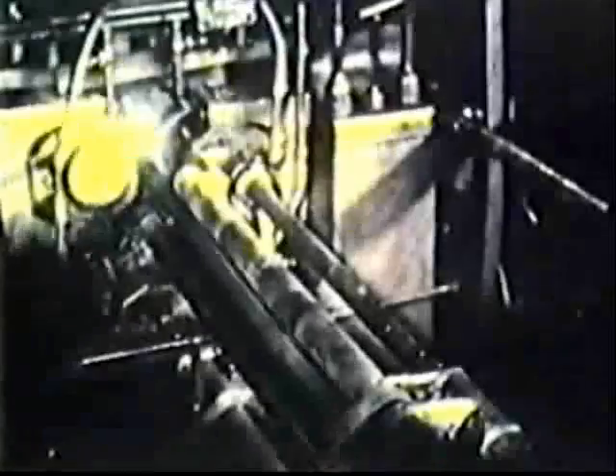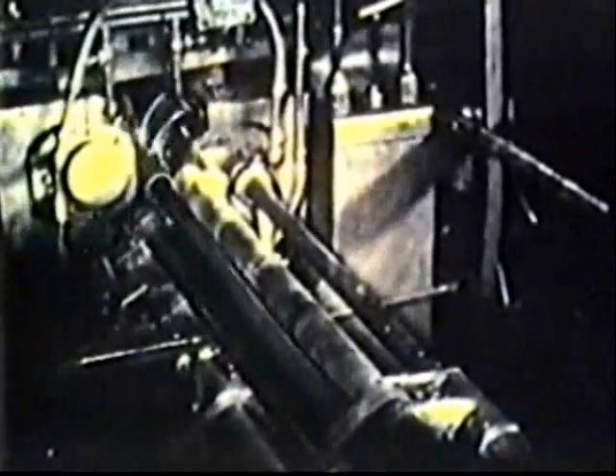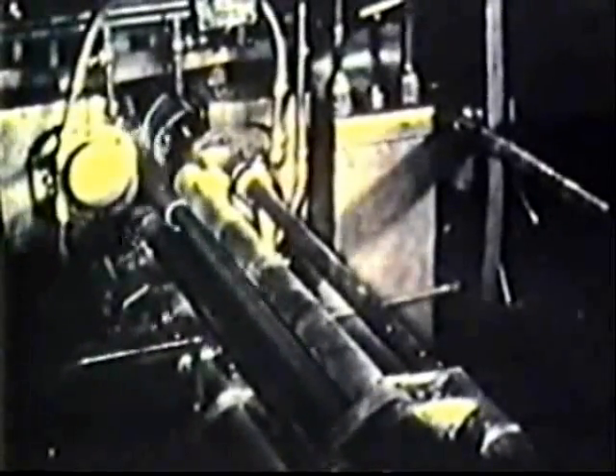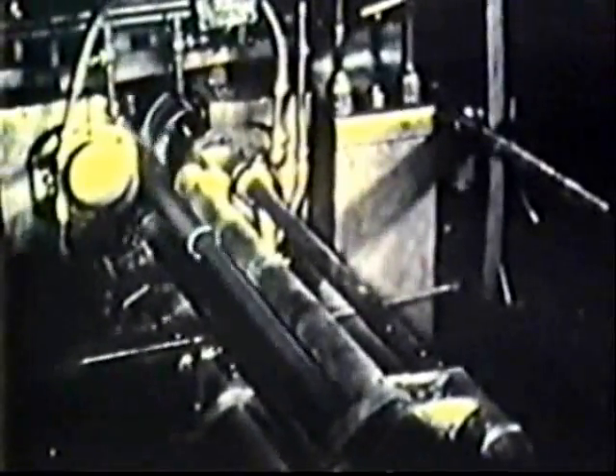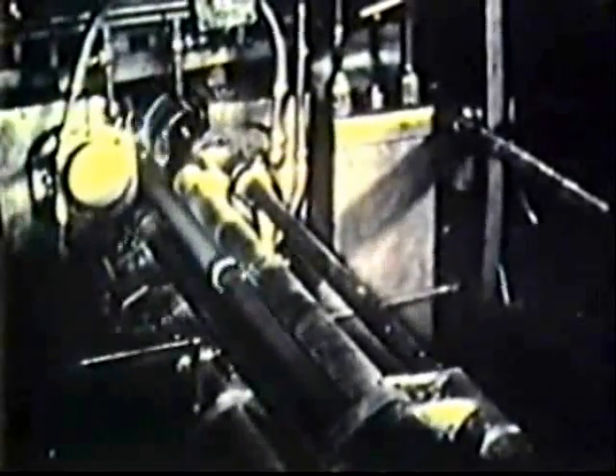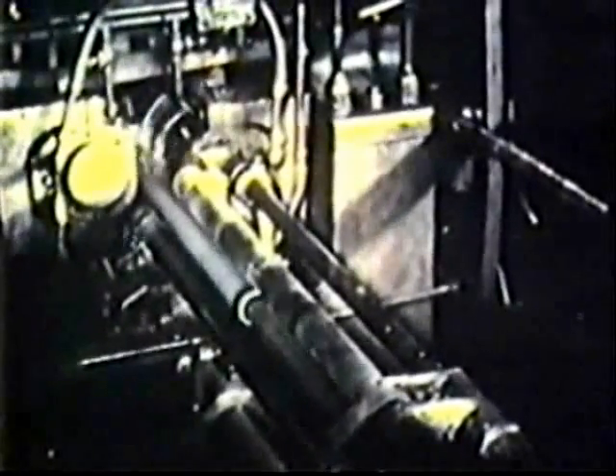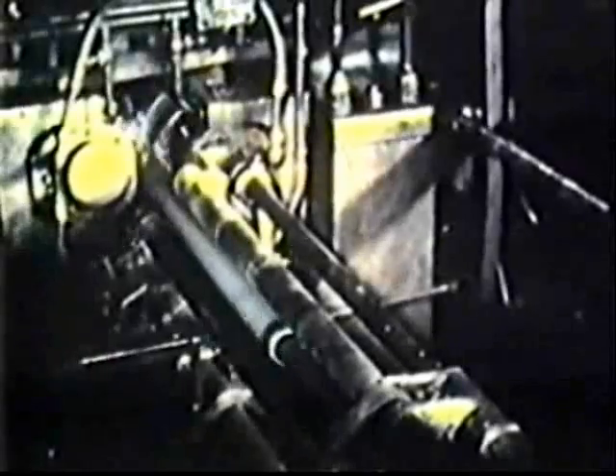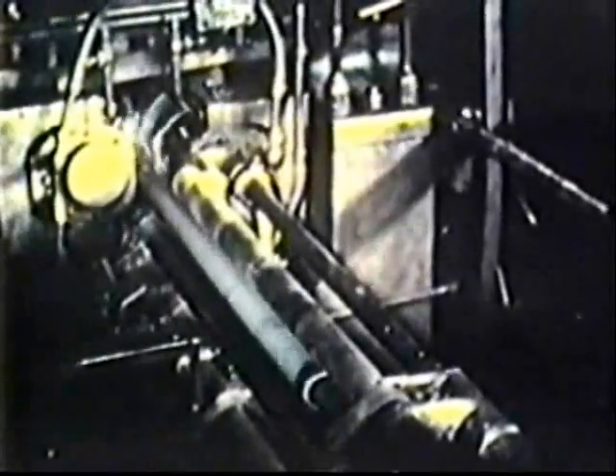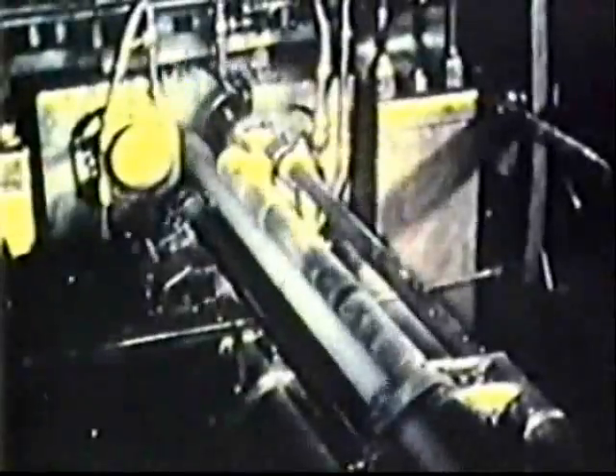When the heated billet emerges from the furnace, it drops into position in a large piercing mill. It is forced between two inclined driving rolls, which break a hole ahead of a pointed mandrel and rod. The mandrel irons the inside surface. This action forms a seamless base tube. They are cooled in a water-quenched tank and made ready for the subsequent operations.